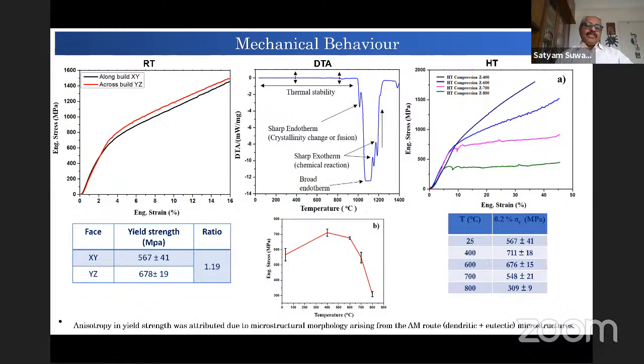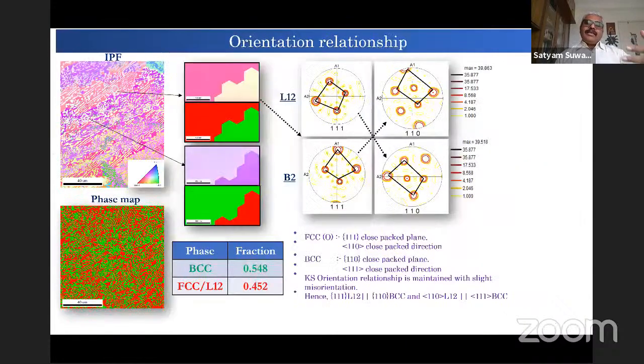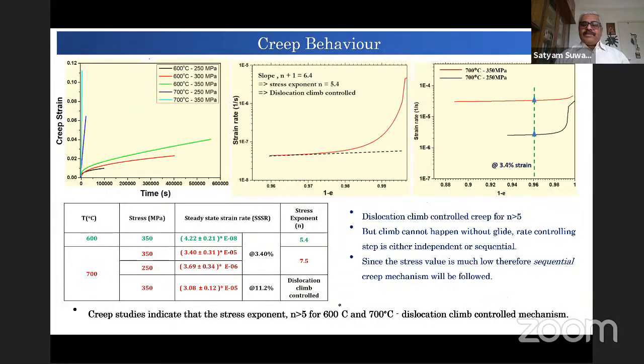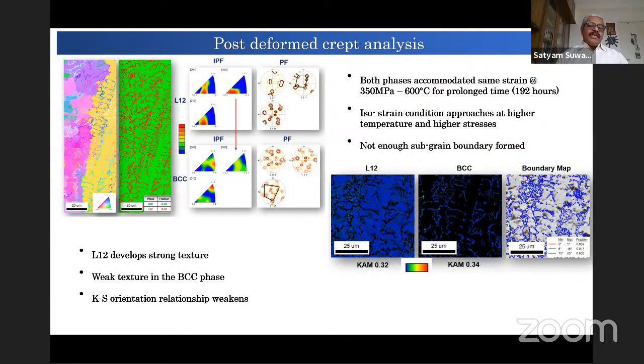We could also examine the orientation relationship in these alloys, and we could see that there is a Kurdjumov-Sachs-type orientation relationship between these two phases initially present in the material. We examined the creep behavior, and we could see the nature of creep mechanisms at 600 and 700 degrees. We also carried out post-deformation creep analysis, and we could see that a weak texture formed, the orientation relationship weakens, and the L12 phase develops a very strong texture in this case.